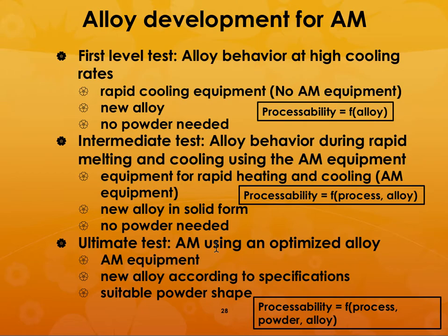Then you need to have an intermediate test and you need to know what is the alloy behavior during rapid melting and cooling using the AM equipment. So again, here you don't need the powder, but you need to know that your processability is going to be a function of the process as well as the alloy itself. And the ultimate test is going to be based on additive manufacturing of the powders itself. And so there you need to optimize the processing conditions of the AM equipment, and then you need to know what kind of microstructures you are going to obtain as a result of the processing.